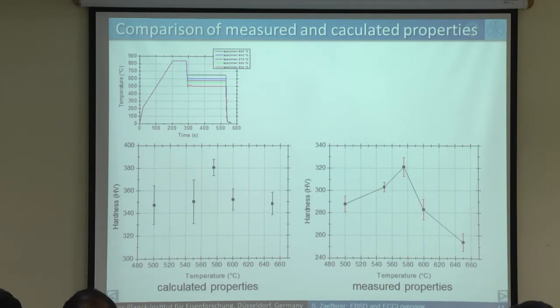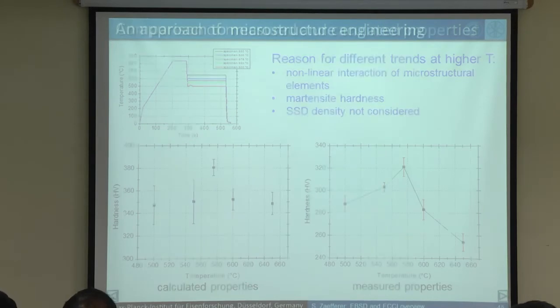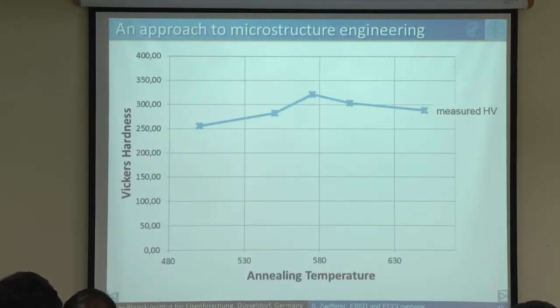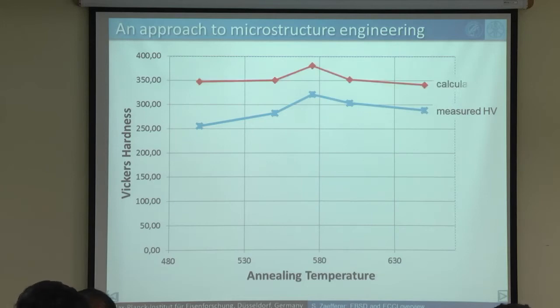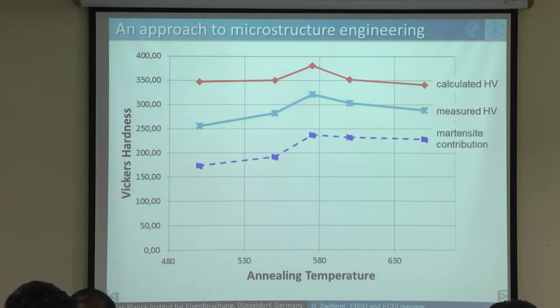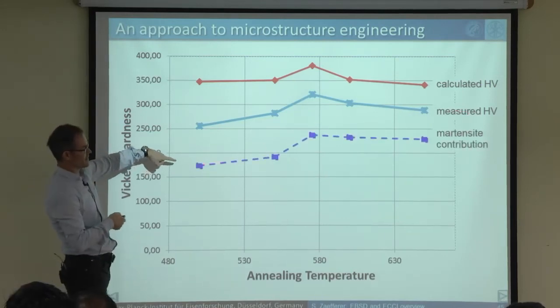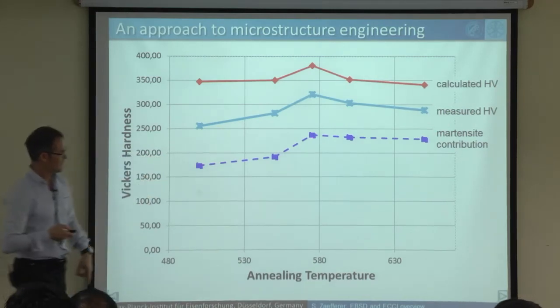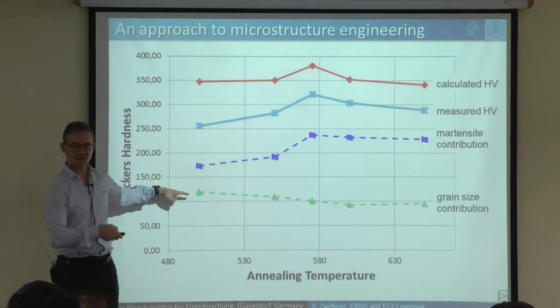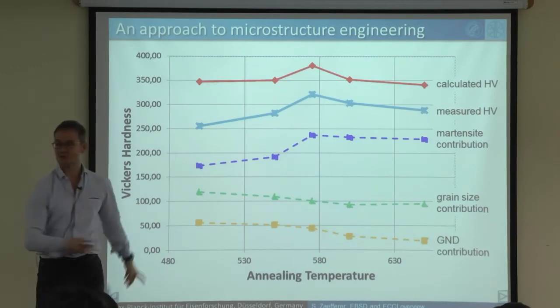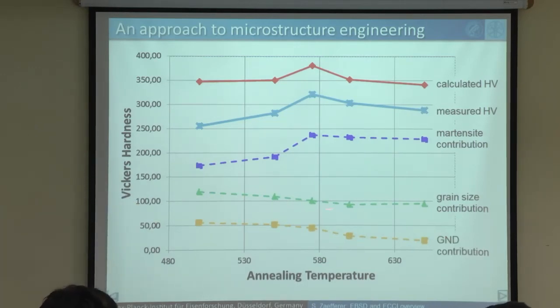And now we can do something very beautiful based on that. Let's switch over that. That's the measured hardness, and that's the calculated hardness. So it looks relatively similar, but not exactly identical. And now we can say, which of these microstructural elements have contributed how much to that? So this one here is the contribution of martensite volume fraction and martensite hardness. This one here is the contribution of grain size, and this one here is the contribution of dislocation density. And if you add all these lines together, you get to this.